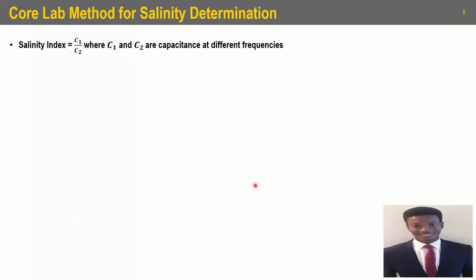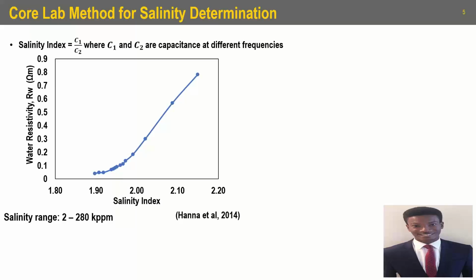So what Core Lab did was that they developed something called the salinity index, which is a ratio of capacitance at different frequencies. And based on this, they developed a calibration curve that takes the water resistivity as a function of salinity index. Now, this salinity index calibration line was determined by measuring Berea sandstone samples that were imbibed in brine of known resistivities. And from those measurements, they were able to build this calibration line.